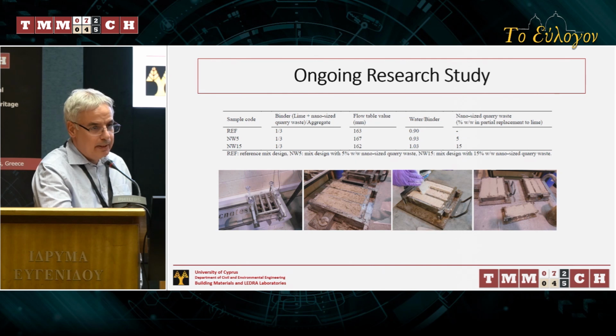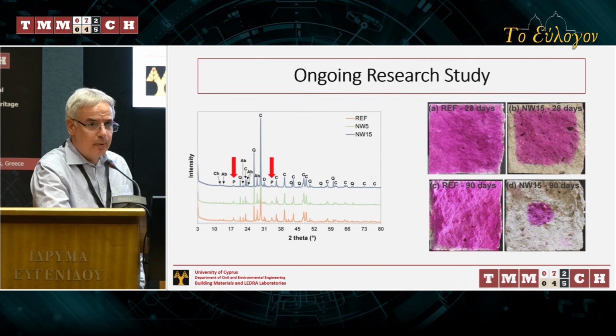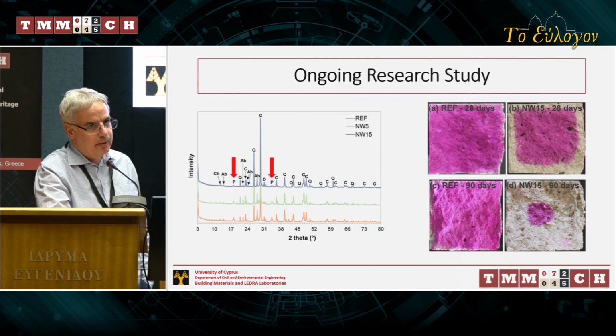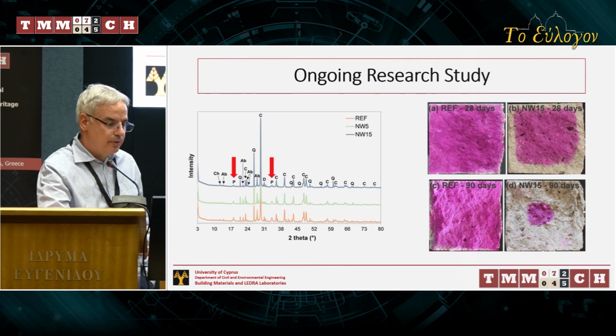So we used this material in producing lime mortars, and we used it as a replacement for the lime binders, not as a replacement for the aggregate. And the results were quite interesting and quite promising. We have shown that in the mix designs with the quarry waste additive, the intensity of the portlandite peaks was almost diminished. And this was an indication that the additive actually reacted with portlandite to produce calcium carbonate.